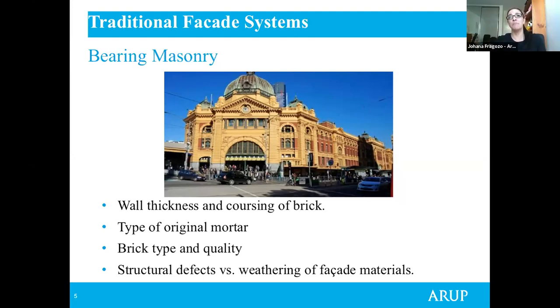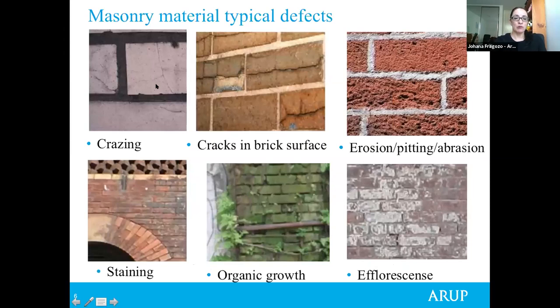So with masonry materials, the typical defects are, we could have some crazing. When we are looking at crazing, we mainly need to look for fine cracks that don't have any sort of clear directional pattern. Some of the possible causes are improper brick manufacture and quality, and this usually occurs in glazed brick. Then cracks in brick surface. In this particular photo, we're looking at cracks that do not go through the mortar joints. And this mainly is a sign that there could be some constraints in the ceramic expansion of the brick, or the brick could have a high saturation rate.